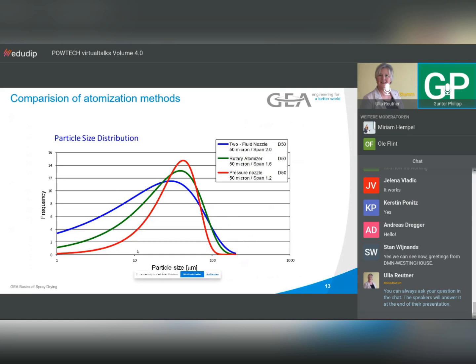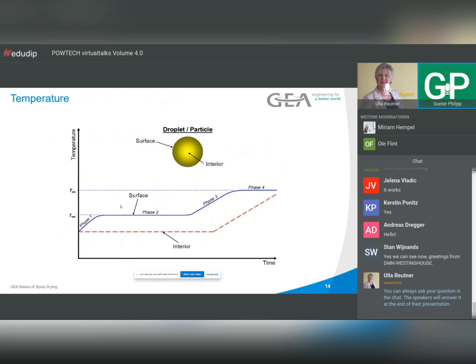This curve shows — with the same median particle size D50 of 50 microns — how the distribution varies for different methods. The pressure nozzle has the narrowest distribution, as I mentioned, while the two-fluid nozzle always has a tail toward the small particles.